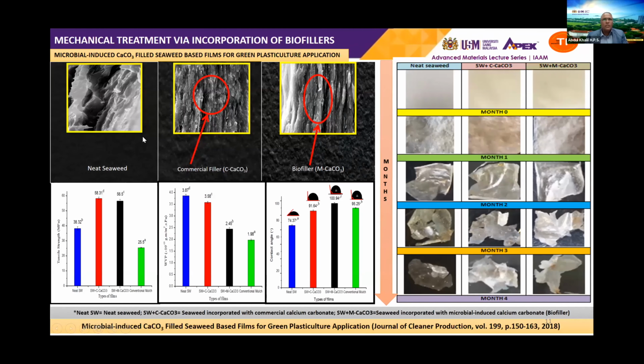Next, we focus on the properties improvement through mechanical treatment. In this study, neat seaweed was reinforced with biofiller generated via microbial-induced calcium carbonate process using Bacillus sphaericus. The results show that the tensile strength incorporated with biofiller had increased by 35%, water barrier increased by 32%, and the contact angles increased by 10%.